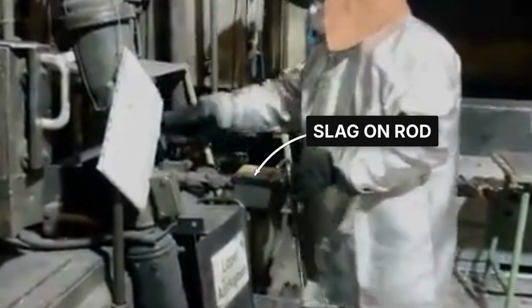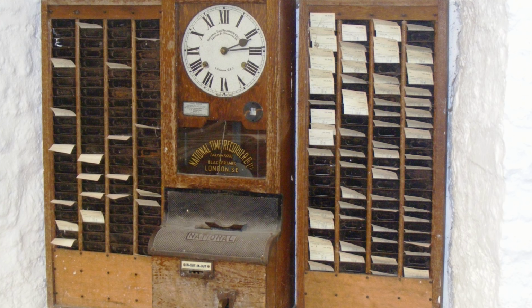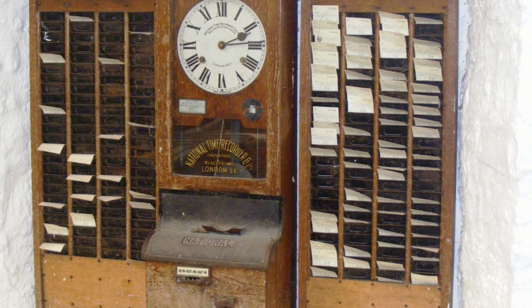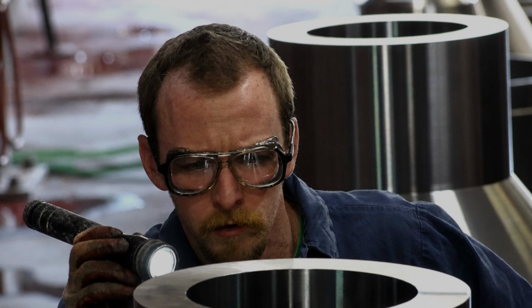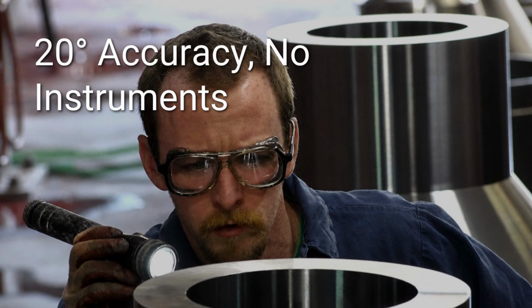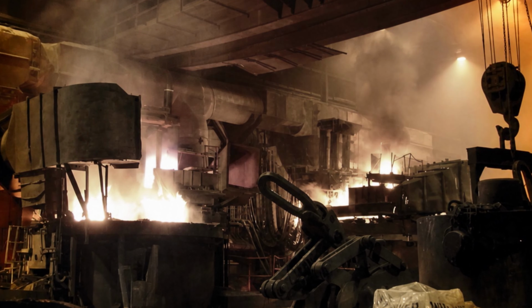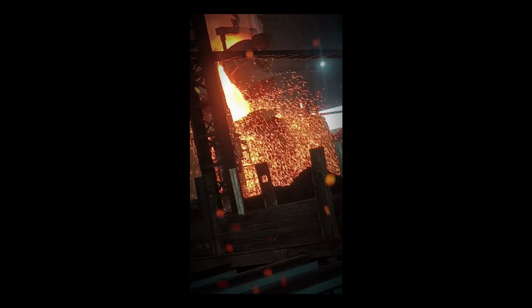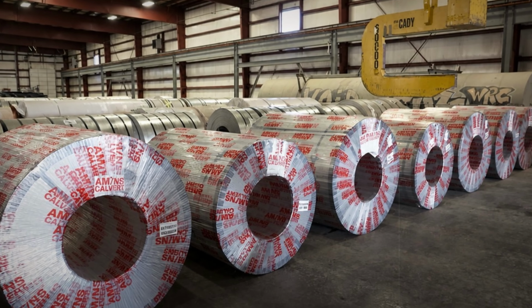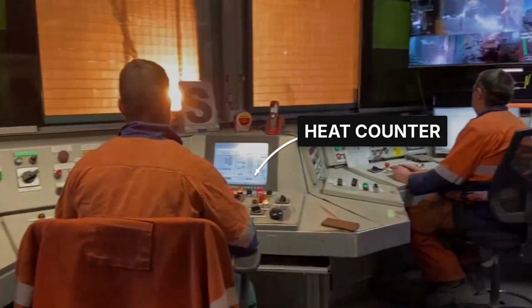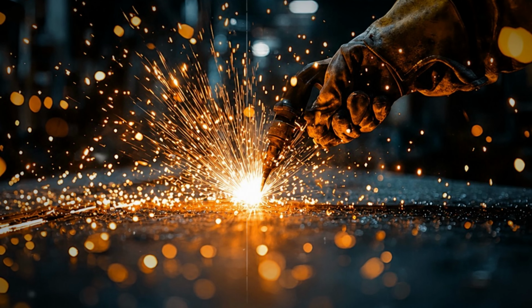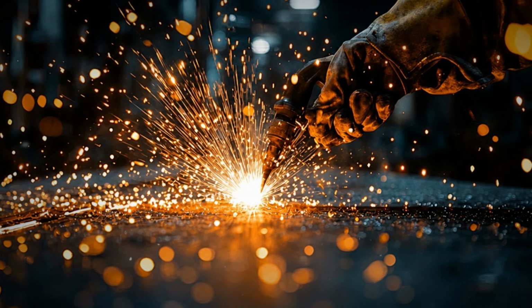A heavy, rolling boil meant carbon still burning. A quieting bath meant the drop was near. He made it by the slag on his rod, the color through his blue glasses, the sound of the furnace, the hours on the clock, and 40 years of heats stored in his head. Temperature within 20 degrees. Carbon within points. No instruments. Tap high and the heat was ruined in the ladle. Tap low and you cooked it back at ruinous cost. The melter carried the value of a house in every judgment, 8 times a turn, and the whole shop moved on his word. He was, by every definition that matters, a human sensor array wired to a human computer, running software written by experience and debugged by fire.